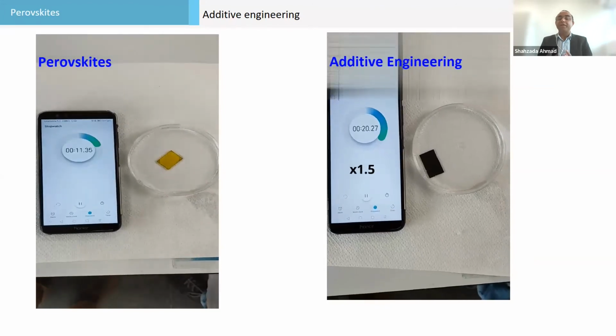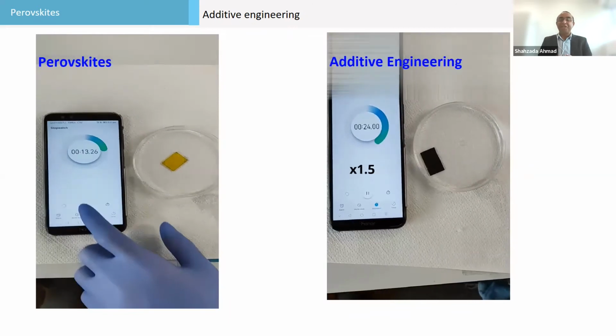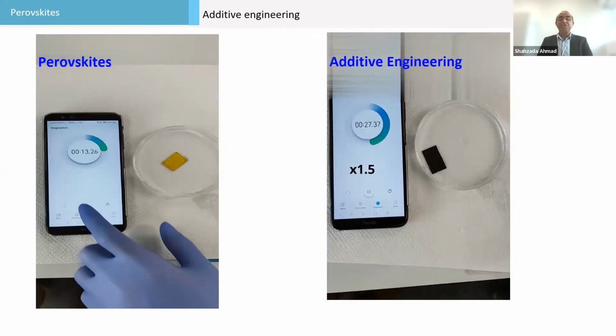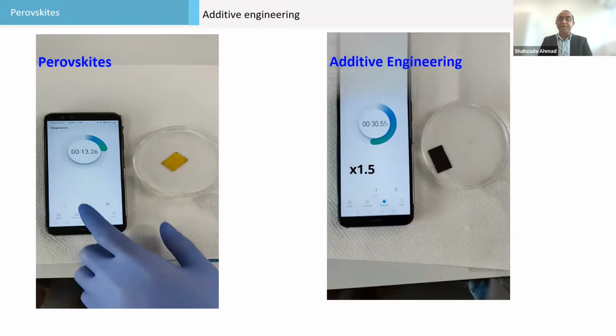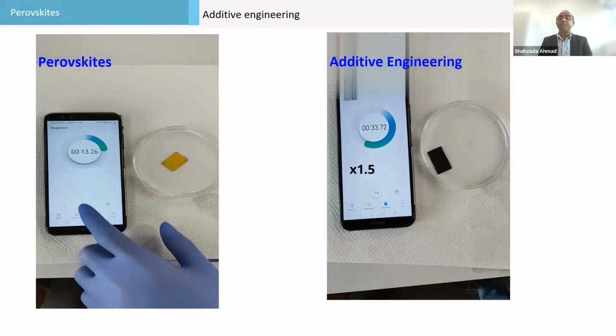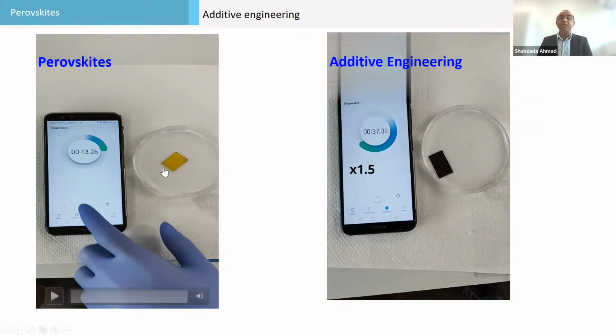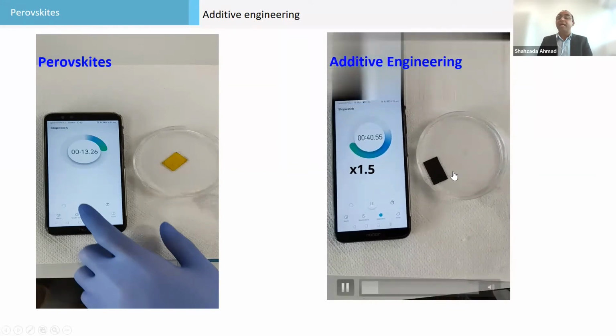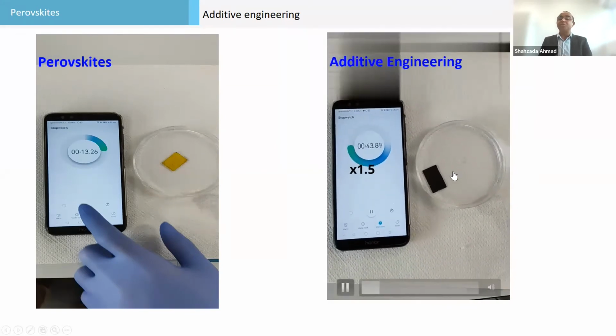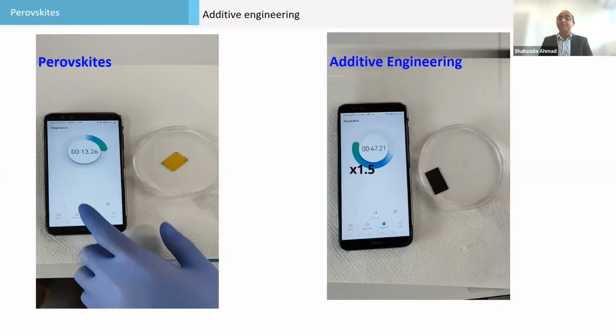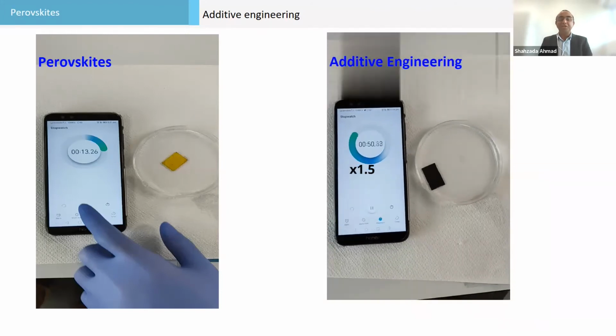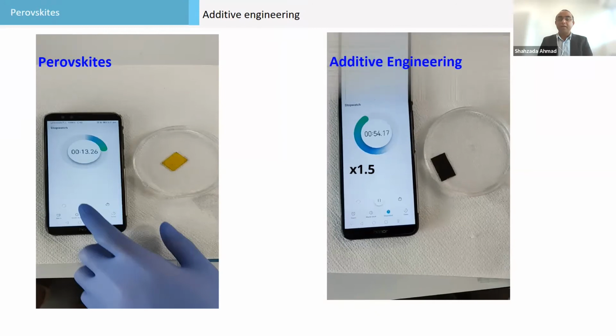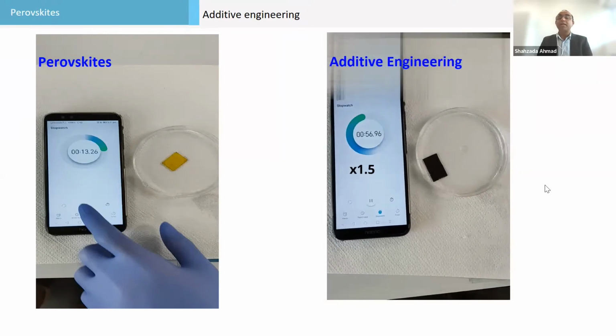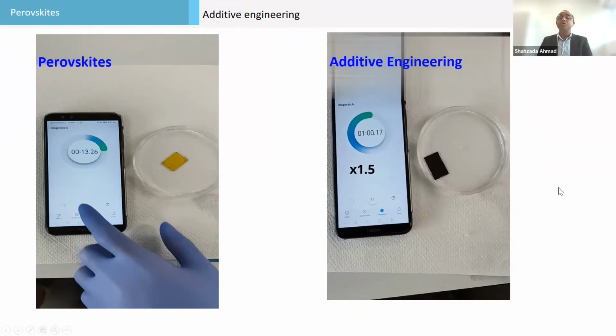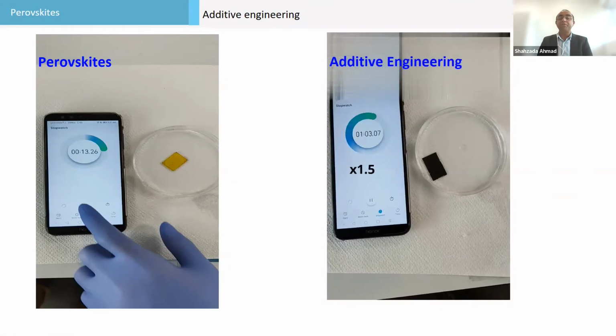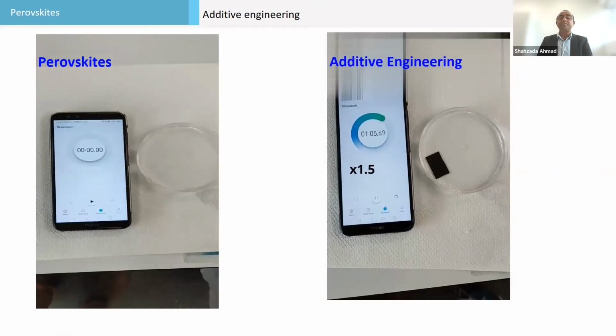So it remains black. But now we are in the process of optimizing the performance. The initial performance is not very attractive, but we are optimizing. You can see the other one became yellow colored, so it will not work, while our additive engineering based sample is still black, so you can expect that the device will be more robust. We have recorded the PL also. Hopefully in another 2 months we will update you with better results.